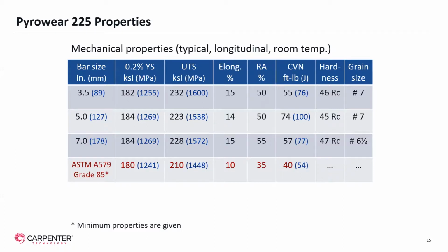Typical mechanical properties of PyroWare 225. These are given in the longitudinal direction, and all these properties at room temperature are given in this slide, where I'm listing 3 different bar sizes, 3.5, 5 inch, and 7 inch, where you can see that the typical yield strength is in the low to mid 180s KSI, with the typical UTS ranging anywhere between the mid 220s to the low 230s KSI. The alloy has good ductility, as seen by its good elongation and reduction of area numbers.